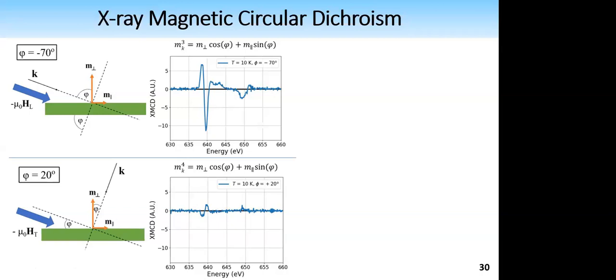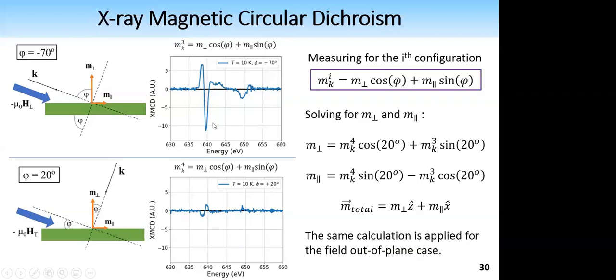From the diagram, the measured moment is a linear combination of the perpendicular and parallel components with coefficients found using trigonometry. Those equations of the moment projected onto the k vector are those two linear combinations. Here I'm also showing the corresponding XMCD spectra taken at 10 Kelvin and 4 Tesla field. Then we can take these equations and solve them as simultaneous equations for m perpendicular and m parallel, and hence we can construct a two-dimensional vector. For out-of-plane field measurements, the calculation is basically the same.